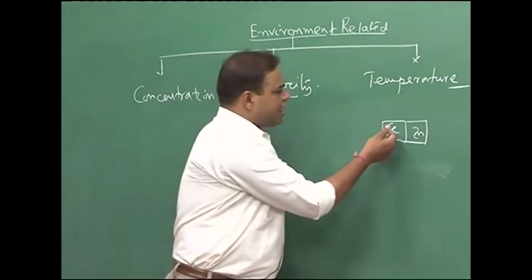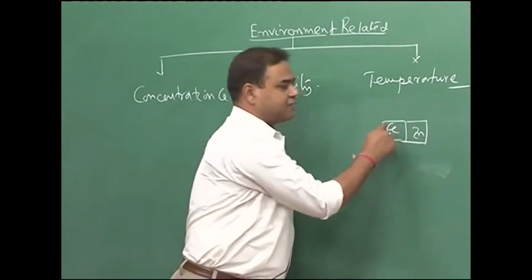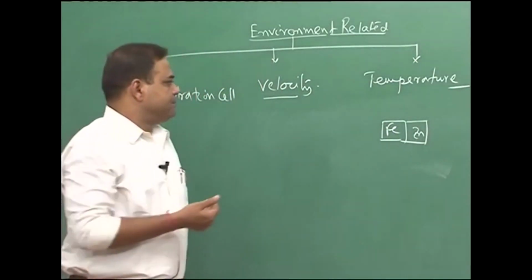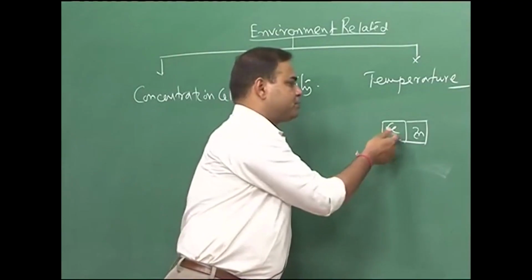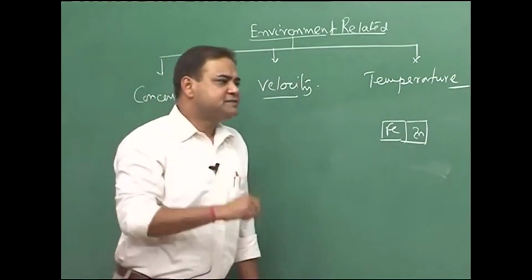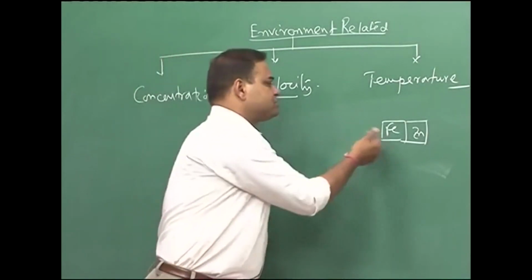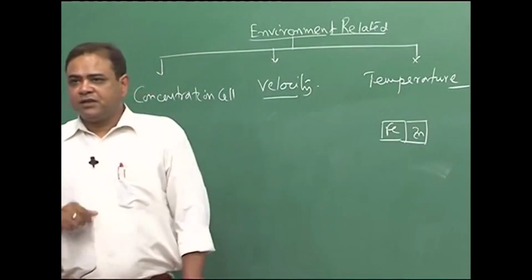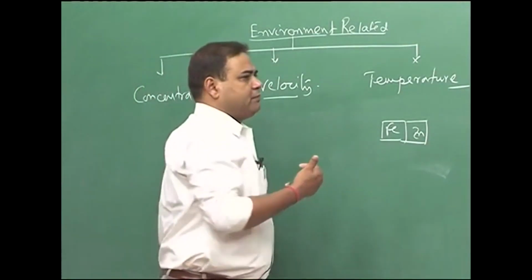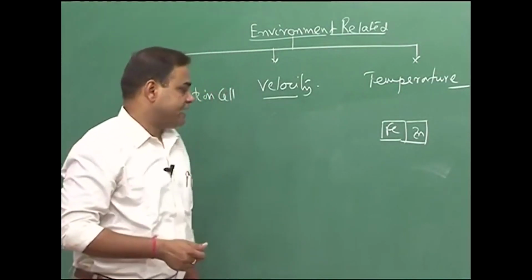In that case iron will corrode, zinc will be protected. Since the zinc oxide layer has formed above some critical temperature, that leads to corrosion of iron instead of protection. So, the temperature is another issue. If we increase the temperature, in most cases the corrosion rate increases, but there could be a possibility of polarity reversal due to the formation of a different passive layer. So, this is the temperature factor.